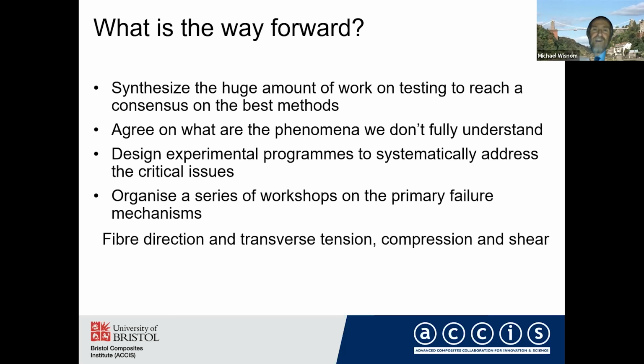That's what we want to do, and I think we're making a lot of progress on that. We've demonstrated that you can go from ply level properties up to the strength of quasi-isotropic specimens with holes, and even recently looking at predicting the R curve in fracture on quasi-isotropic laminates. So I think we're making a lot of progress, although there's still some areas which are not fully captured.